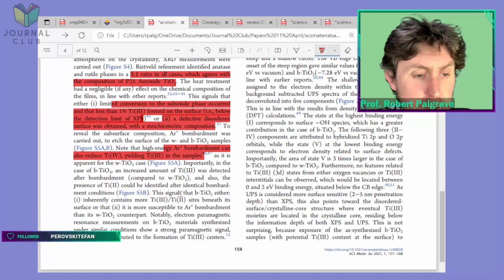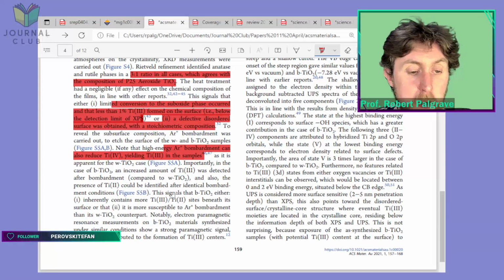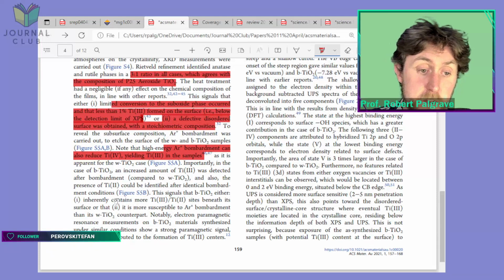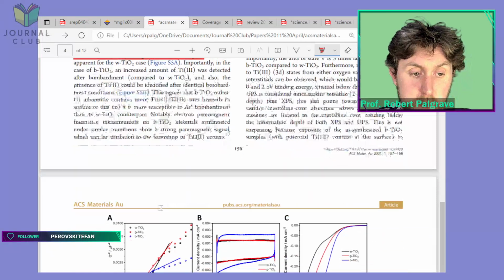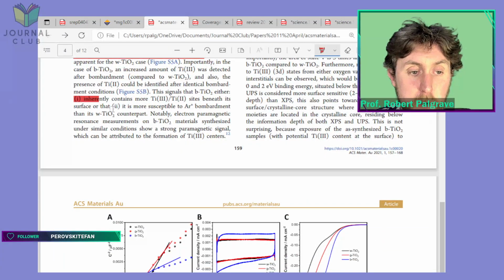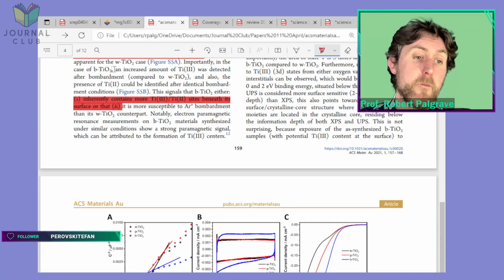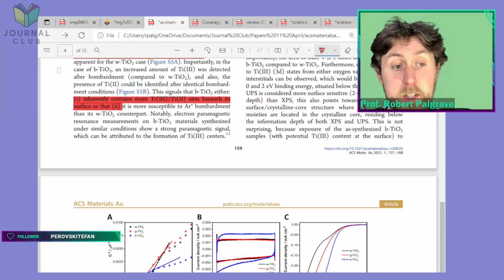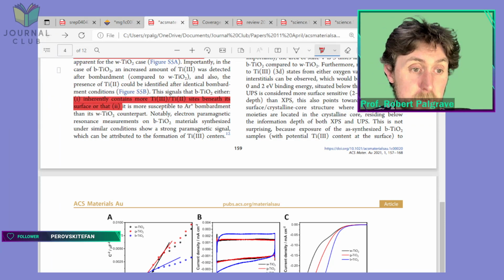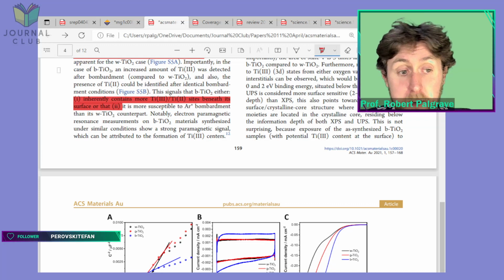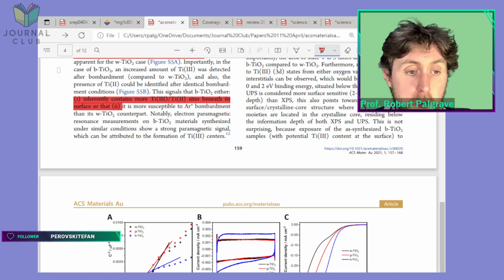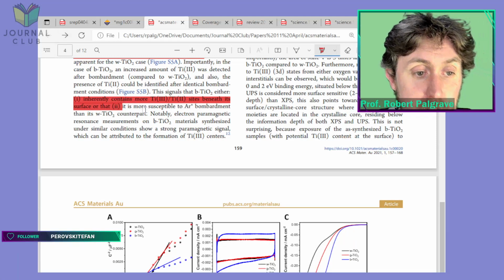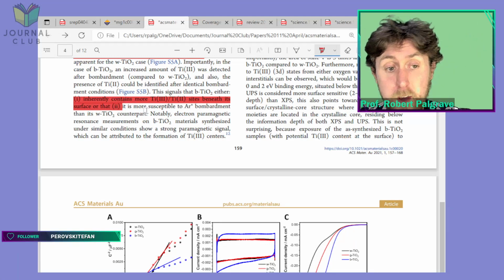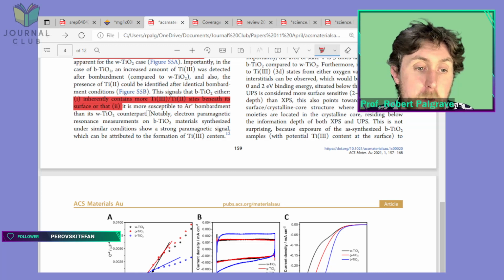So this signals that black TiO2 either inherently contains more Ti3+ and Ti2+ sites beneath the surface, or that it's more susceptible to bombardment. I actually quite like this approach. I like the fact that they've done it a couple of times now. They've made an observation and then given different possibilities about what it could be. I think that's pretty effective here. I think those are probably the two main reasons. I don't really see how else that could happen unless there's a difference in the argon ion bombardment, but we can believe they did the experiment carefully, so hopefully there won't be.